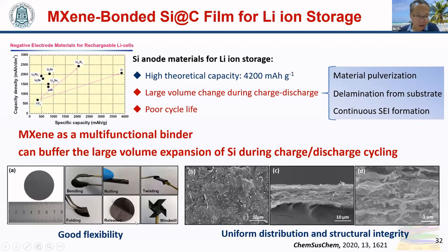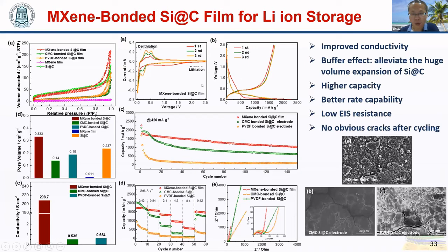As a multifunctional binder, in this case, MXene can not only provide good conductivity and better ion transportation, but most importantly, it can construct a loose and porous structure to buffer the large volume expansion of silicon during the charge-discharge cycle. This is a very important property for silicon electrodes. It can improve the cycle performance. With the improved conductivity and buffer effect, this MXene bonded carbon-coated silicon film shows higher capacity, better rate performance, and much lower resistance. SEM indicates no obvious cracks were observed after long cycling measurements, much better than the conventional CMC and PVDF bonded electrodes.